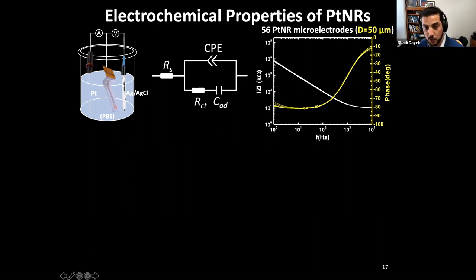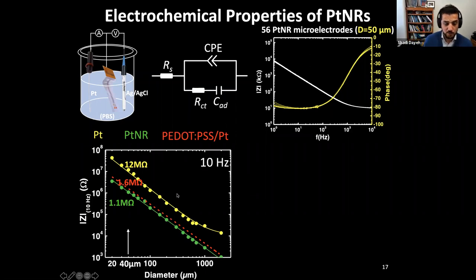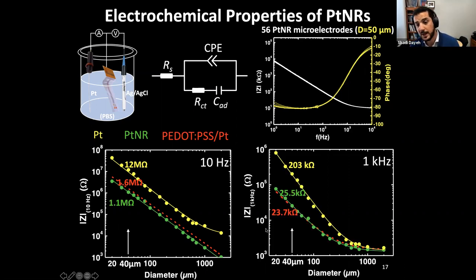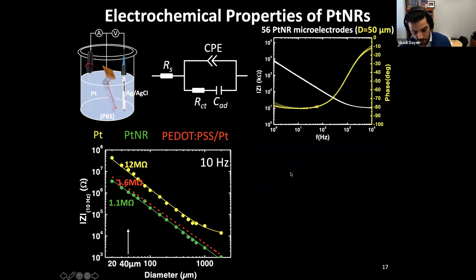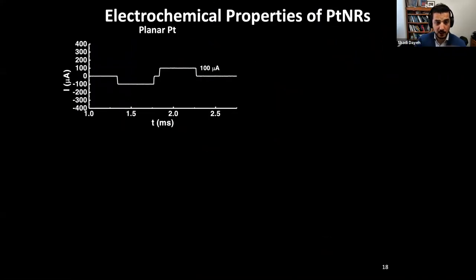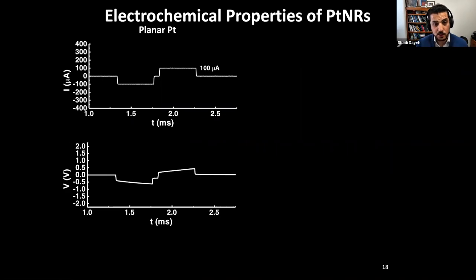And so the impedance as a function of frequency usually goes as 1/f. So we have capacitive dominance at low frequencies, and then it's dominated by the series resistances at higher frequencies. Now, we want to benchmark the platinum nanorods with respect to commonly known electrodes, planar platinum for instance, or PEDOT:PSS. This is the impedance magnitude at 10 hertz, and it's lower than that of PEDOT or platinum. And at 1 kilohertz, it's equivalent to that of PEDOT and much lower than that of platinum. So that's what gave rise to the low 1/f noise in the plots or the spectra that we've seen earlier. The low impedance is also important for the stimulation.